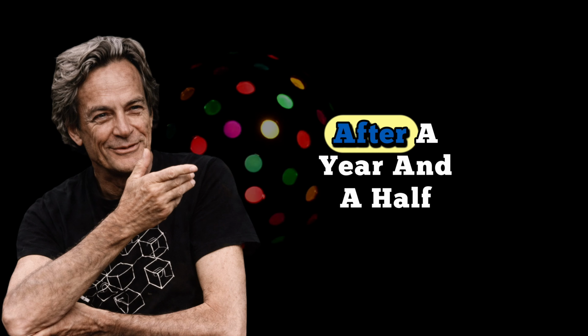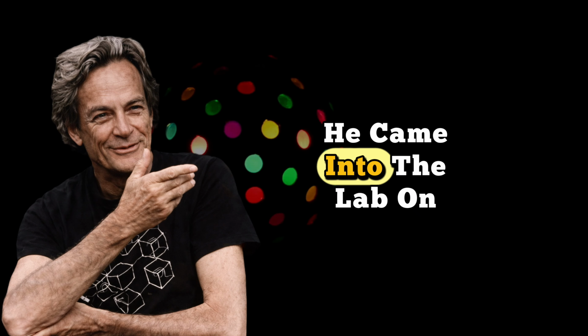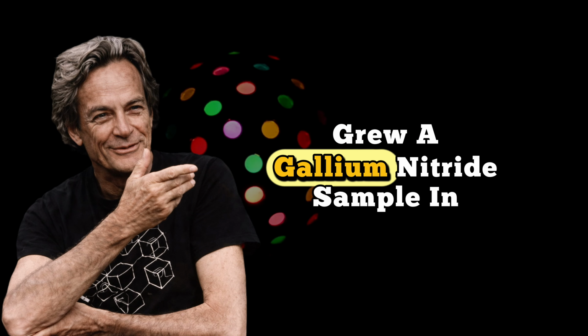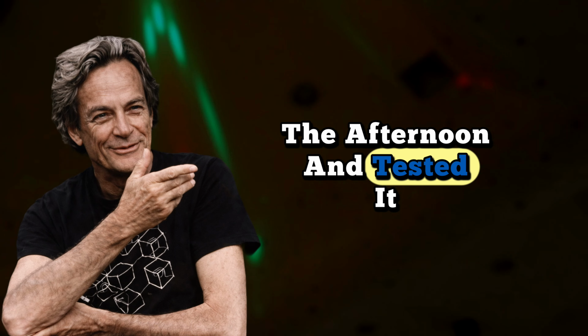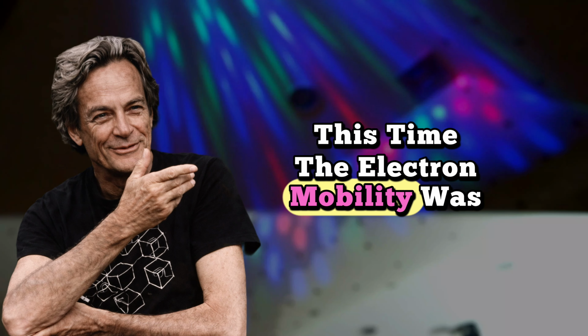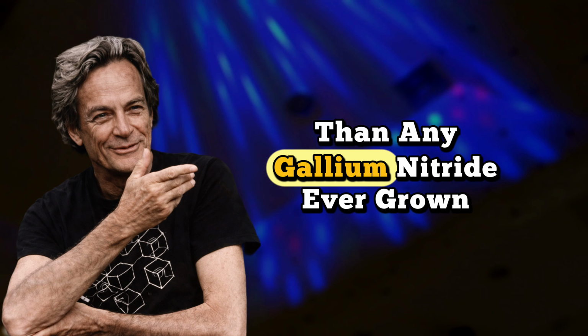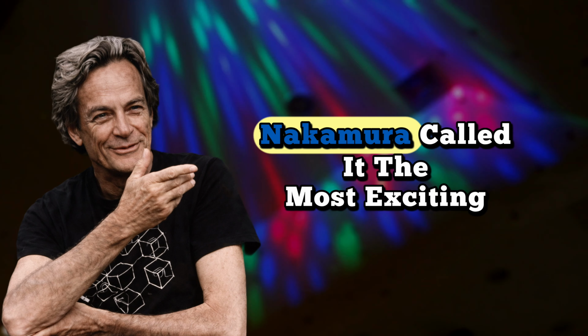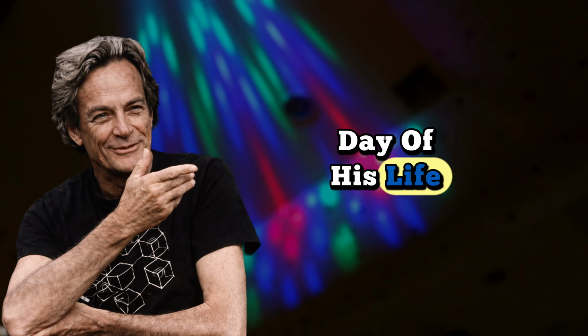After a year and a half of continuous work, he came into the lab on a winter day in late 1990. As usual, he tinkered in the morning, grew a gallium nitride sample in the afternoon, and tested it. This time, the electron mobility was 4 times higher than any gallium nitride ever grown directly on sapphire. Nakamura called it the most exciting day of his life. His trick: adding a second nozzle to the MOCVD reactor.